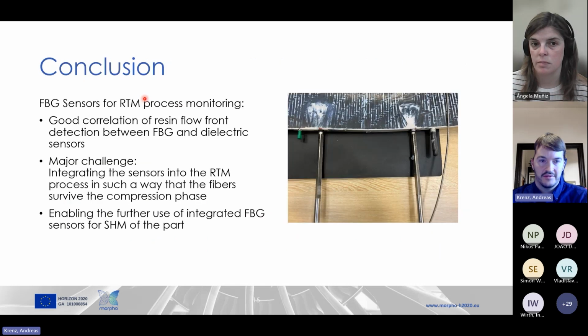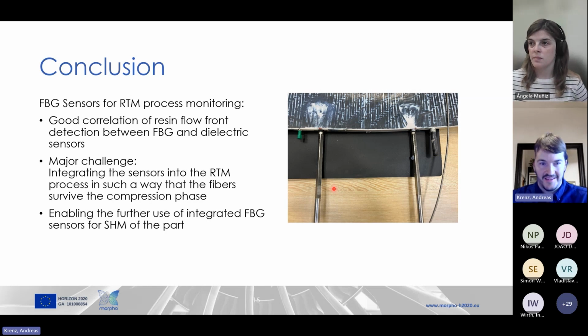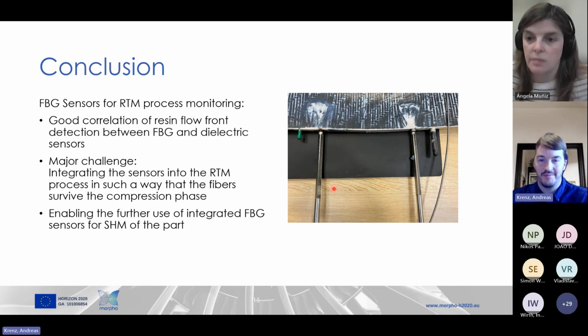Okay, and to my last slide, as I mentioned, the FBG sensors for the RTM process monitoring have a good correlation of the resin flow between the optical and the electrical sensors. The major challenge was integrating the sensors in such a way that the fiber survives the compression phase of the RTM process and enables the further use of the FBGs for the SHM later on. And this simple photo on this final slide required a considerable amount of research and also several iteration loops to finally succeed in manufacturing fully functional optical fibers in this FOD panel, which survived the harsh RTM process environment.